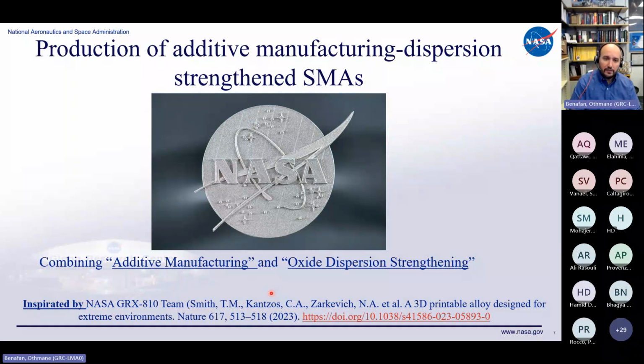Now the mechanisms are different. In shape memory alloys, we have martensitic transformations. In the structural alloys, you don't have that, and you are counting on the types of dislocation interactions. That's how you get your strengthening. So in our case here, we have strengthening, but we also have martensitic transformation. So you have compatibility between the austenite and martensite that you have to worry about. You have things like nucleation of martensite and growth of martensite once it's nucleated. So those things, in addition to dislocation interactions, come into play when doing such a method for shape memory alloys.